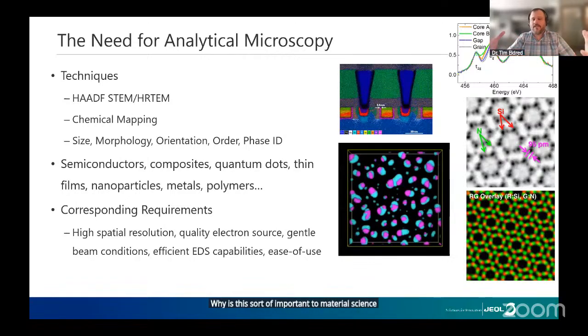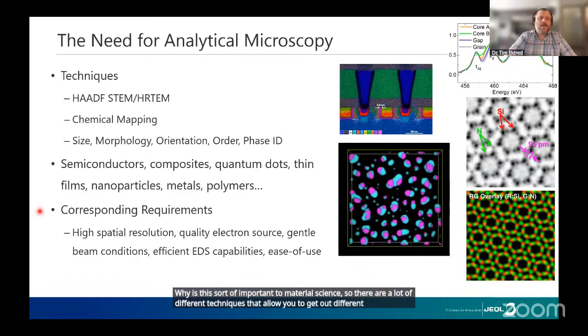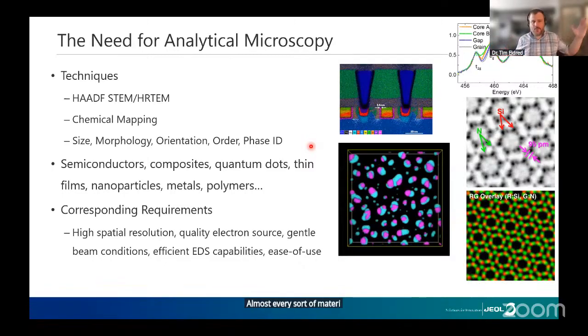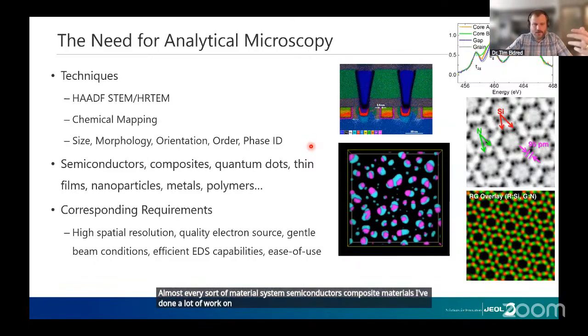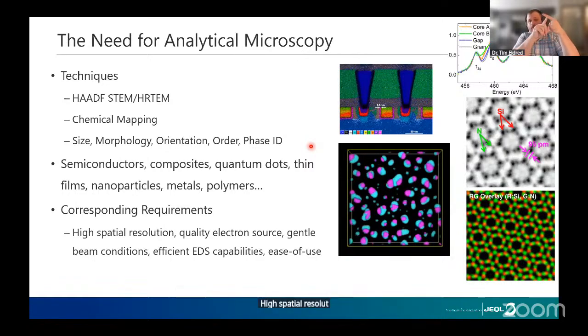So there are a lot of different techniques that allow you to get out different information. In addition to just the atomic resolution imaging, we can do chemical mapping. We can look at size, morphology of grains, nanoparticles. We can look at the phases of these materials. We can apply this to almost every sort of material system, semiconductors, composite materials. I've done a lot of work on nanoparticles and metals, but the requirements for this are high spatial resolution. You need a quality instrument, and you need to take care of how you're irradiating material with electrons.